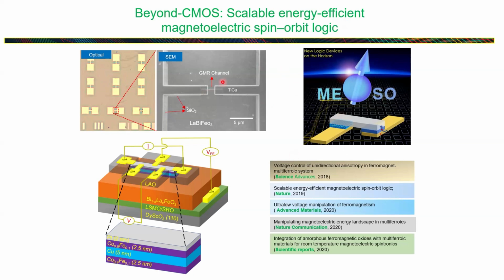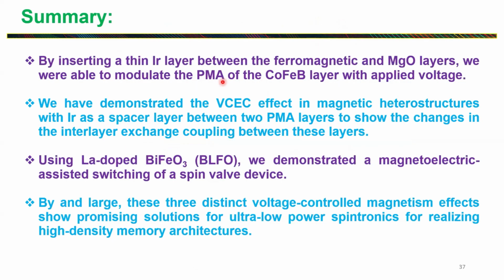Okay, so this is a summary of my talk. I have shown that by inserting a thin iridium layer between the ferromagnet and the MgO layer, one can modulate the PMA of the cobalt iron boron layer with applied voltage. We have also demonstrated that one can modulate the interlayer exchange coupling with the voltage in a magnetic heterostructure where we use iridium as a spacer layer between the